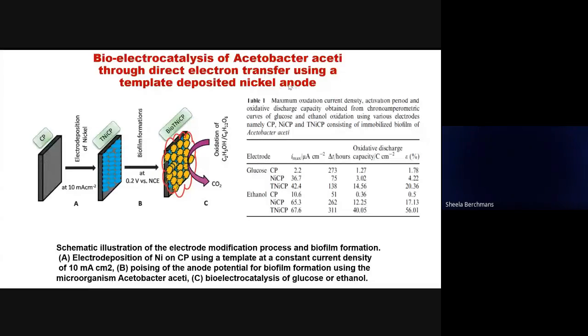Then later on, we studied the bioelectrocatalysis of Acetobacter aceti by direct electron transfer using template deposited nickel anode. So we made use of carbon paper over which nickel was electro deposited using a template, and over which biofilm was formed, and the electrical current generation property of this electrode was studied. You can see the maximum current that is produced in presence of carbon paper compared with templated nickel carbon paper. You can see from 2.2 to 42.4. The current has increased to a large extent.